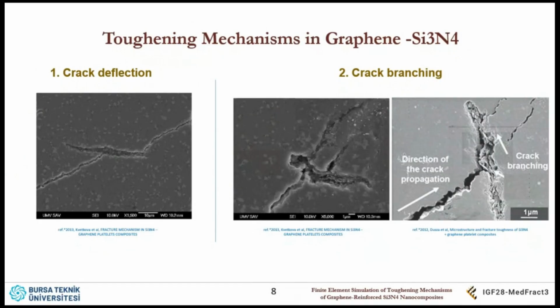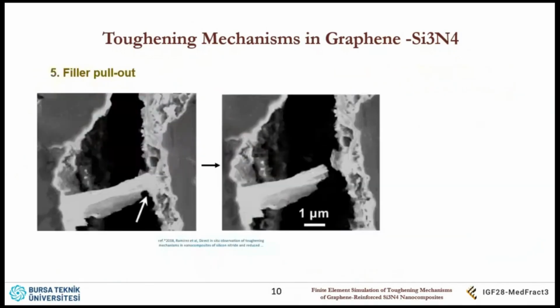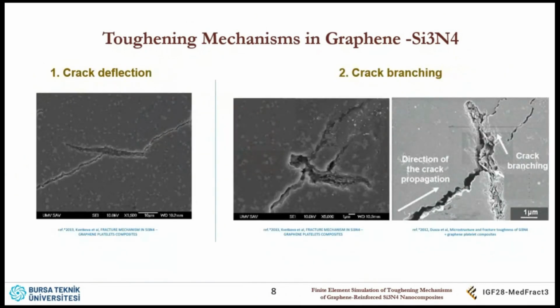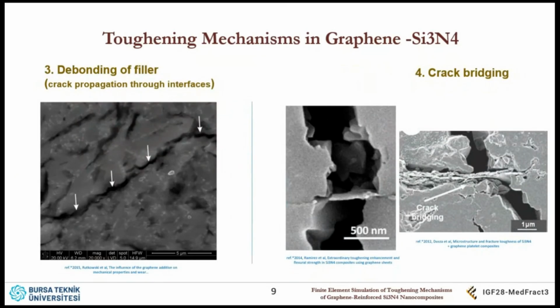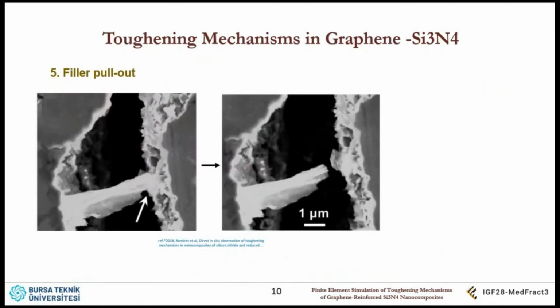So I researched the literature and found 5 major mechanisms. The most fundamental one is crack deflection. And then crack branching. As you see, the crack propagates, hits the graphene and separates into two. The third one is debonding of the filler. If you can notice, this is a graphene, but there is debonding through the crack path. It is happening between the graphene and the matrix. And fourth, crack bridging and filler pull-out. All of these mechanisms help the material absorb more deformation energy.